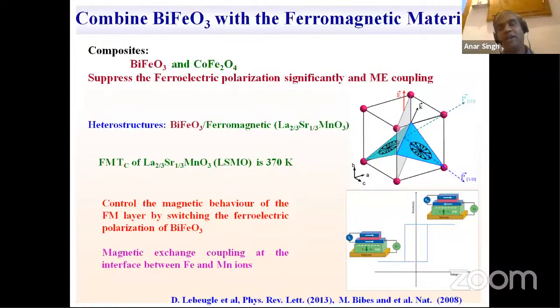So the advantage is that we are trying to get the ferromagnetic component and magnetoelectric effect at room temperature, so that a device can be made. The idea behind making this heterostructure is that in bismuth ferrite, if we change the polarization from one plane to another plane by applying an electric field, the spin rotation plane also changes. So by modifying the spin rotation plane of bismuth ferrite, we can also change the magnetic property of the whole system by interface effect between the magnetic ions like Fe and Mn.